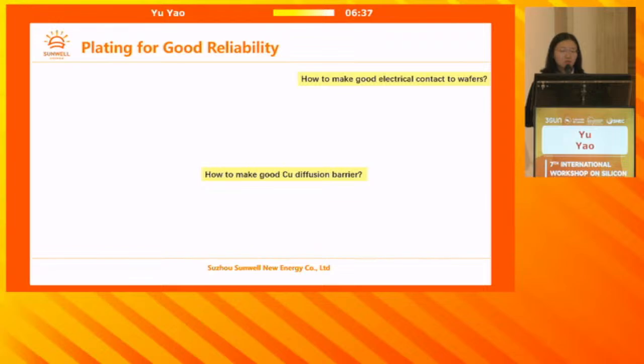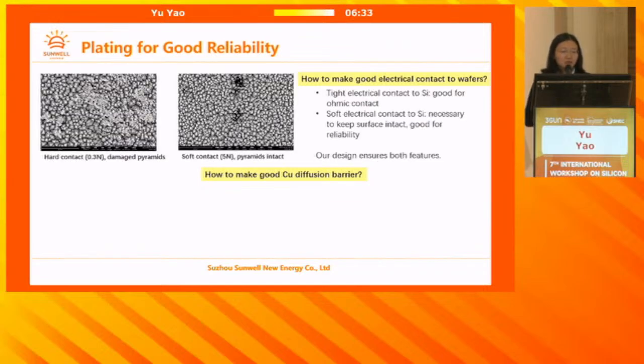So plating for good reliability, in our point of view, has 2 key questions. First is how to make good electrical contact to wafers. It needs to have a tight electrical contact to make sure that it's ohmic contact, but it also has to be soft in a sense that it doesn't damage the pyramids. We presented last year that with a hard contact, like small pins, even with 0.3 Newton of force, you will find some tips of the pyramids being damaged. The risk there is usually that these are the areas where it has plated metal, so it's not active under electroluminescence or photoluminescence. You are not going to see that there is metal covering the pyramids, but you might see problems during the reliability test. So that's one of the key problems we solved in our production line.